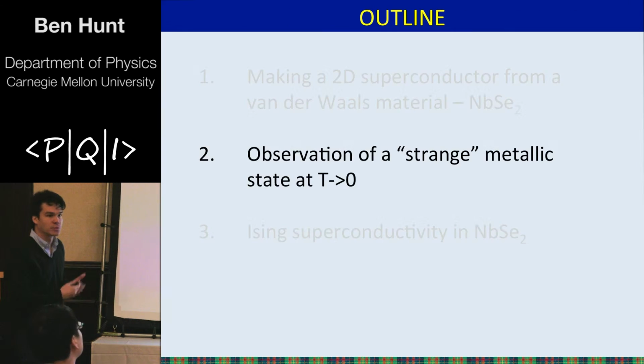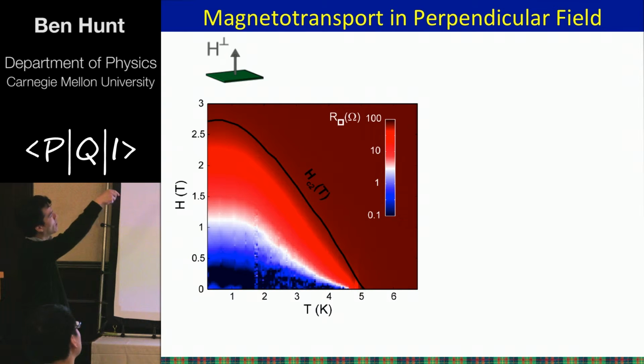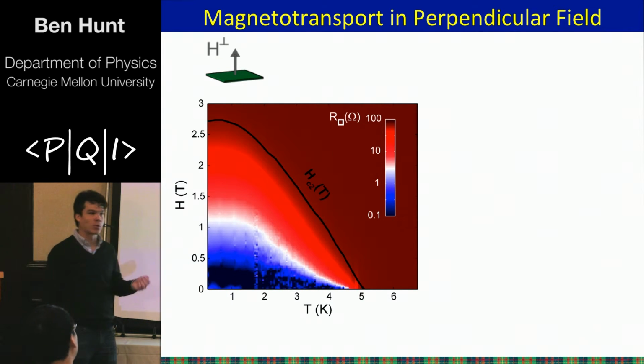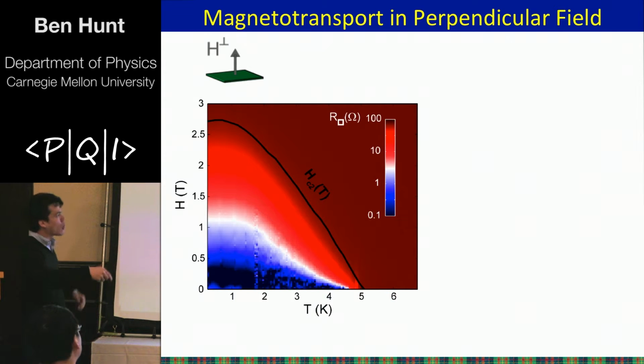Now I'd like to turn to sort of our new observations. So this isn't a great color scale, I guess, for this projector, but what you should be able to see here is a large red region. This is, by the way, the resistance of the sample. A large red region where we see the normal state, where we've quenched the superconductor, right? In a normal transition, what you would expect would be to see this entire region kind of a dark blue color, a superconducting state. But what you see is actually quite a large range of resistance in this, where we would expect to see the superconducting state.